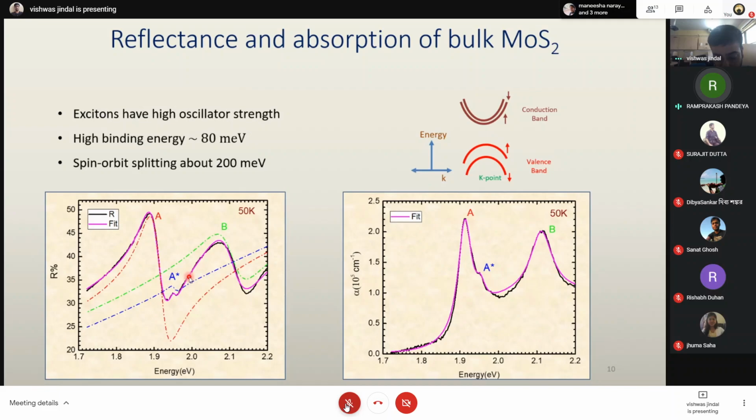Because they are becoming sharper, the band gap is also increasing. This is a general formula for all semiconductors. There's actually an equation, I forgot the name, with which you can model how much the shift is with temperature and calculate some parameters also. You can correlate the phonons in your system with the shift of the band gap.